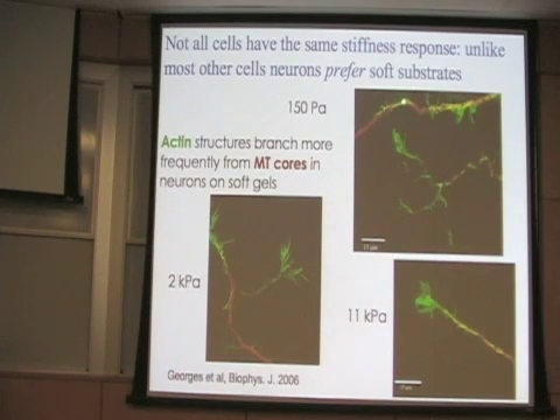It extends a lot of these red stained microtubule bundles, or the core of the axon, but off of it emanate these large branches of green labeled actin, one of which will become the growth cone that will drive the thing forward, and some of which will become branches to allow these neurites to explore more of their space. As the substrate gets stiffer, but no chemical change happens, branching density goes down, and the rate at which these extensions go out also slows down. And even on very rigid substrates, you can get them to grow, but they'll very rarely branch, and they'll grow somewhat reluctantly. So this is the opposite trend.